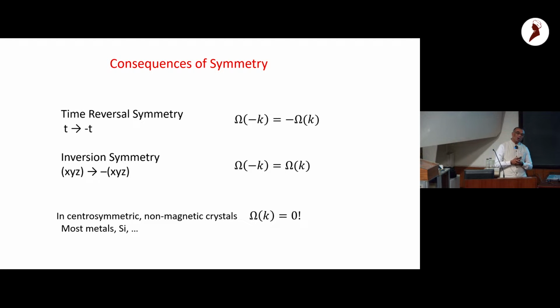The reason why these are not commonplace yet is because time reversal symmetry means Berry curvature omega is odd, inversion symmetry means it's even, and in centrosymmetric non-magnetic systems, it means Berry curvature is identically zero. It's zero at all k vectors, which means most metals are centrosymmetric, and if they are non-magnetic, you won't see these effects at all. Silicon and many other materials are centrosymmetric and non-magnetic. These quantities will not be visible at all.